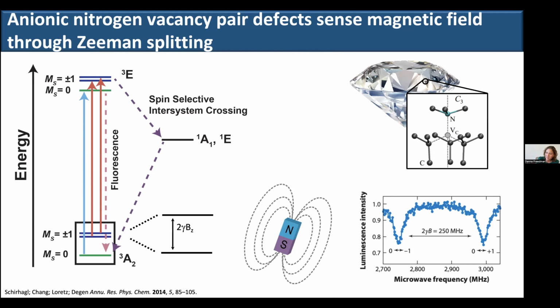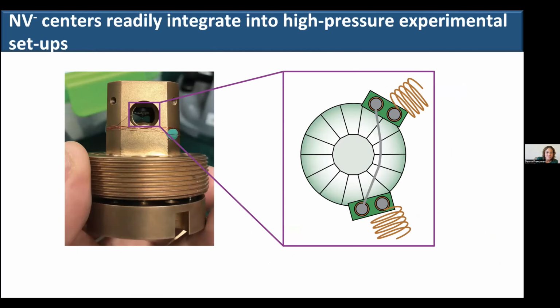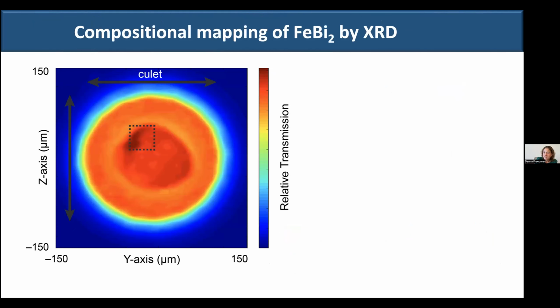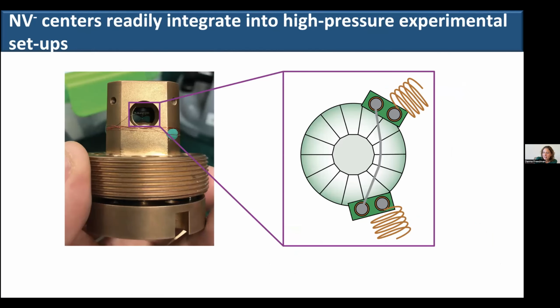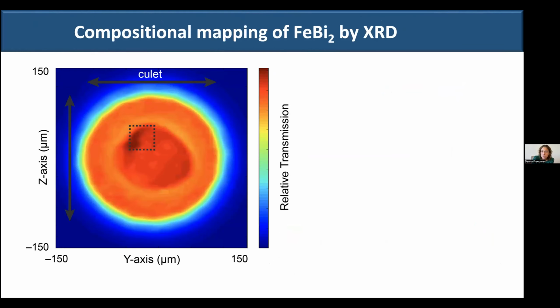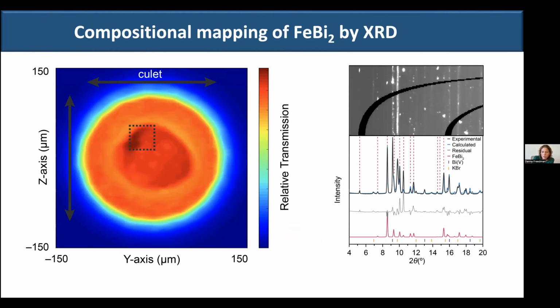So I'm not going to show you any data. I'm just going to say that we can integrate diamonds that have defects into diamond anvil cells, and we can wire them up for microwave measurements. We can also compositionally map iron bismuth by powder diffraction. And by compositionally mapping this, we can compare the magnetic map with the structural map, which is really powerful. We can effectively rasterize this space and measure the structure at every point and the local magnetic moment at every point to make sure that we're measuring iron bismuth.